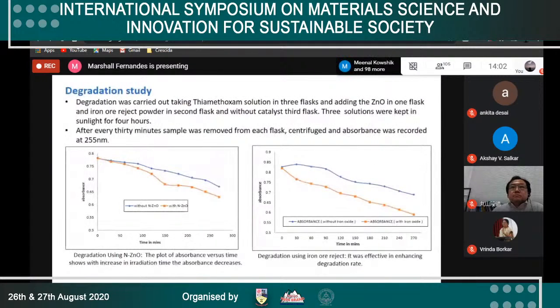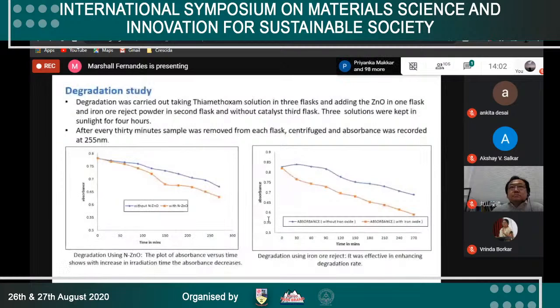Flask without photocatalyst. Three solutions were kept in sunlight for 4 hours. After every 30 minutes, a sample was recorded for absorbance. The first graph of absorbance versus time shows that in presence of nitrogen-doped zinc oxide photocatalyst there is a better degradation rate when compared with the absence of photocatalyst. A similar trend was observed for iron oxide photocatalyst.